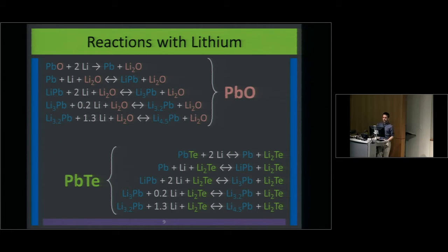One thing to note is that the lead oxide, the very first reaction, is irreversible. So once you go from lead oxide to lithium oxide, that reaction is irreversible and doesn't go back. You lose a lot of capacity there. With lead telluride, once you form lithium telluride, you can actually extract the lithium back out of that, and so you gain some extra capacity there.